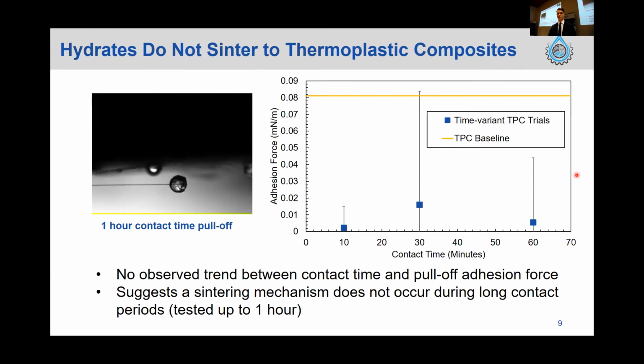And as you can see, not a lot of difference there at all between that and the previous slide, not a lot of adhesion force. So this figure here shows the adhesion force on the vertical axis, and then the contact time on the horizontal axis. So the 3 contact times that were measured and investigated in this research were 10, 30, and 60 minutes, within which time for other materials, namely carbon steel, there was a relationship that was definitely found.